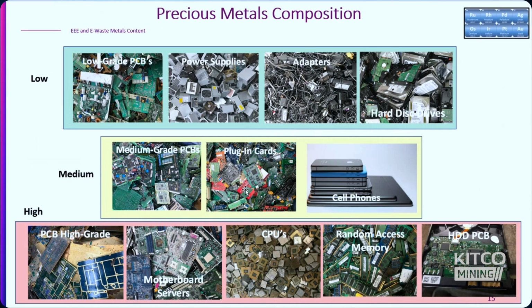Yeah, it is actually. And the reason is that we can extract copper out of these materials with a very low energy and low cost process. And that is why I believe, and don't underestimate copper value in printed circuit boards, 20% of PCBs are copper, and we have almost the same value of gold and copper in printed circuit. So the value is pretty high on the copper side. And if you can extract the copper in an economical way, then that's the key. And that's why I believe our process will be attractive to recyclers and OEMs.